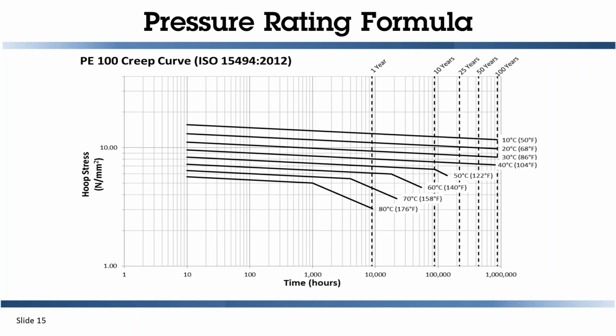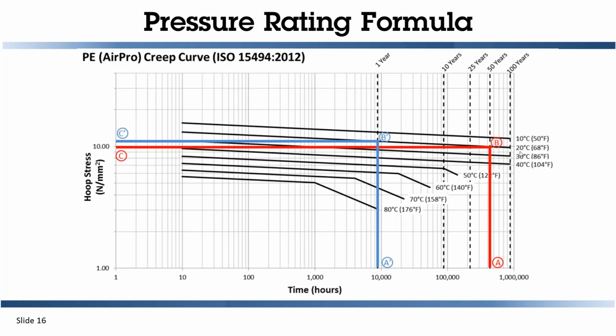This chart here is called a creep curve. It's specific to the type of material. And then you'll also note different temperature ranges on the right-hand side. So we have 10 degrees and 20 degrees. Let's take a look at the 20-degree curve here. So that's pretty much ambient temperature. If we consider the lifetime expected on the bottom, the time, which is hours to failure, we look out at a 50-year lifetime, and then you see A, you move up to B, you have a value, and then move across to the axis, and you get a value of 10 at C.